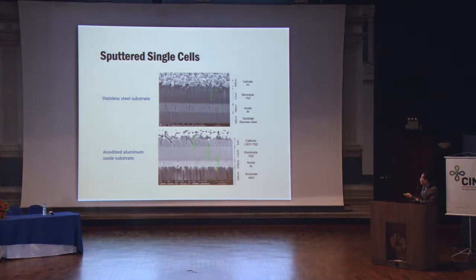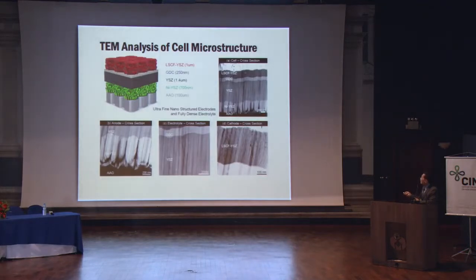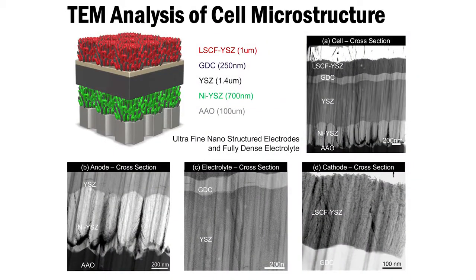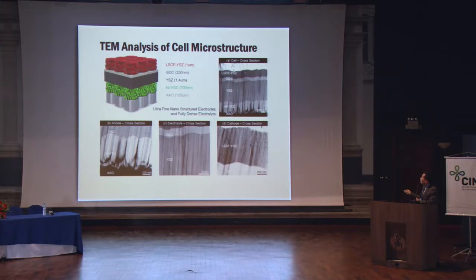Before we show the performance of the cell, here is the TEM analysis of the cell microstructure, and you can see here, in this case, we also have what we call the interlayer, the gadolinium-doped ceria, to prevent the interaction between LSCF and YSZ. So we have a fully dense YSZ, fully dense GDC, porous LSCF, and porous nickel YSZ. Here we show the high magnification of the anode and also the cathode.